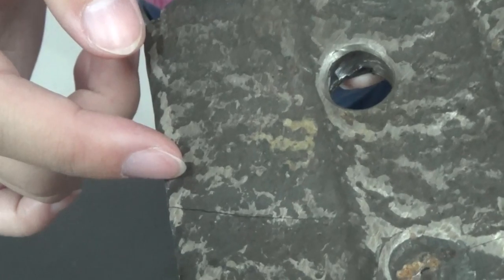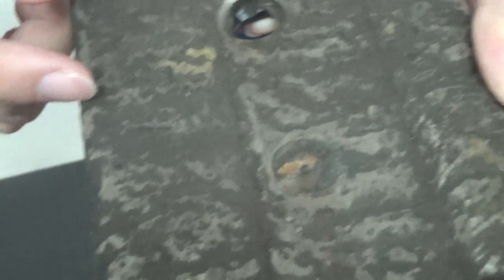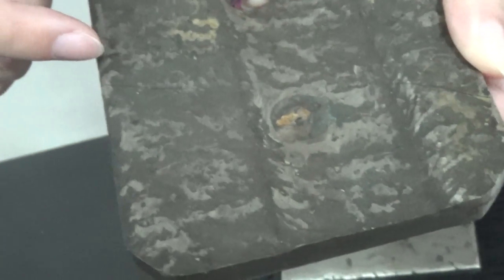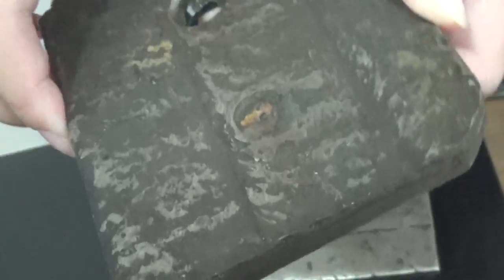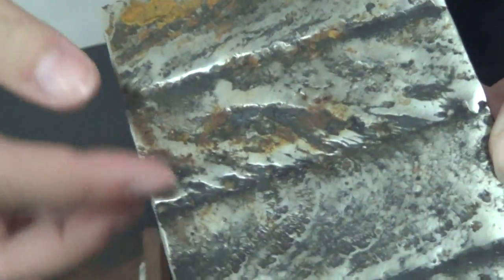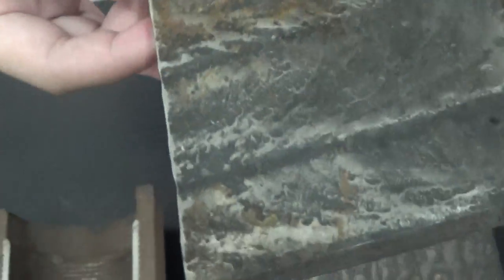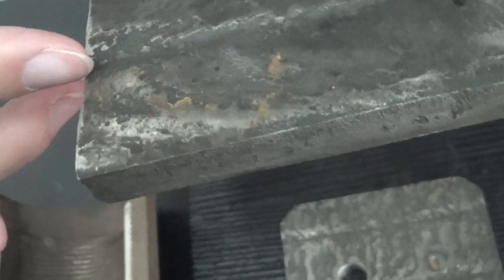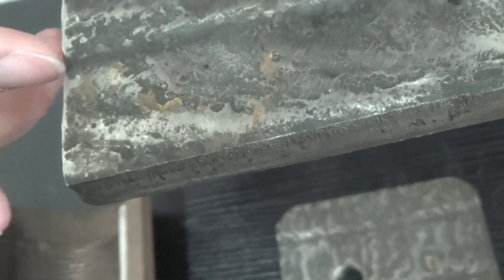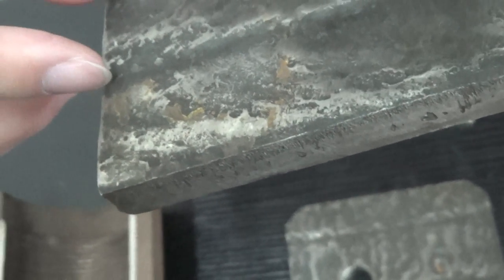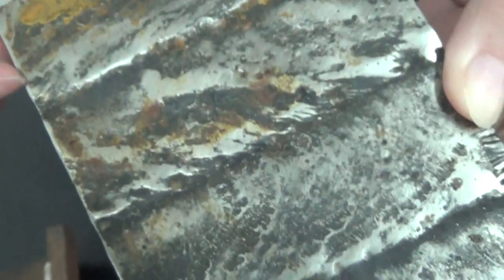There are some micro cracks on the wear-resistant layer. They only exist on the wear-resistant layer, not extended to the base layer. There are some welding patterns on the wear-resistant layer. The normal length of the welding pattern is 35 mm. We can narrow or extend the length of the welding patterns by requirement.